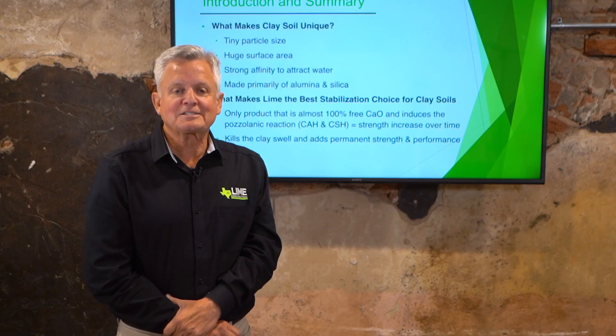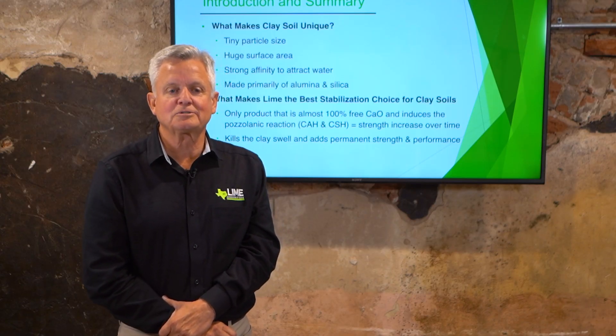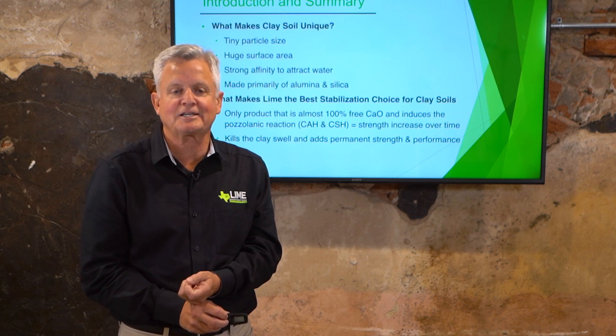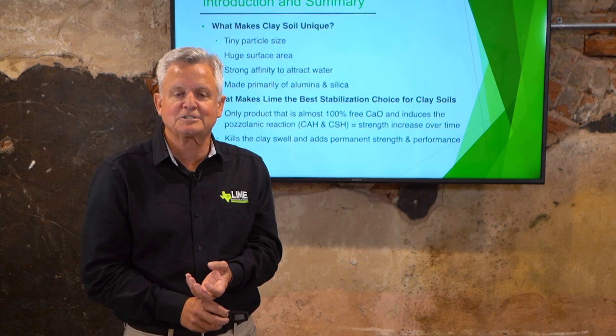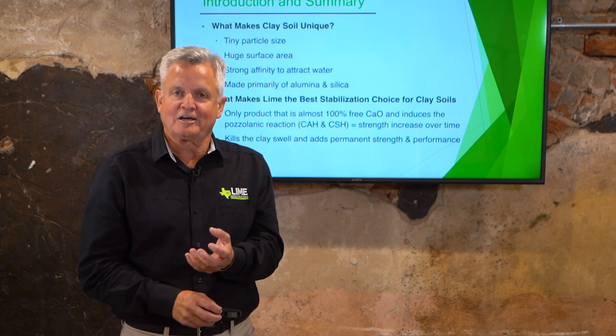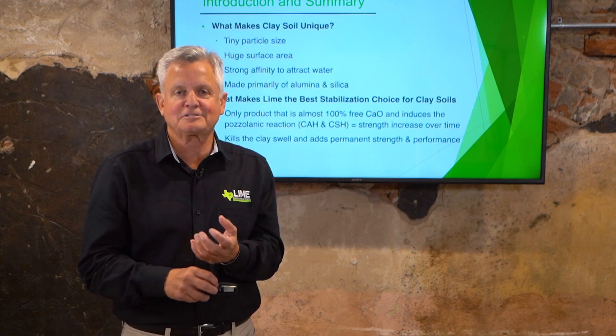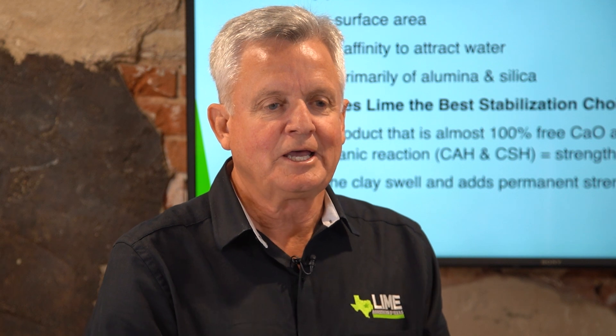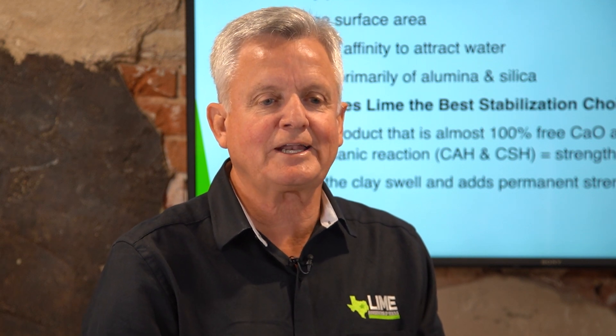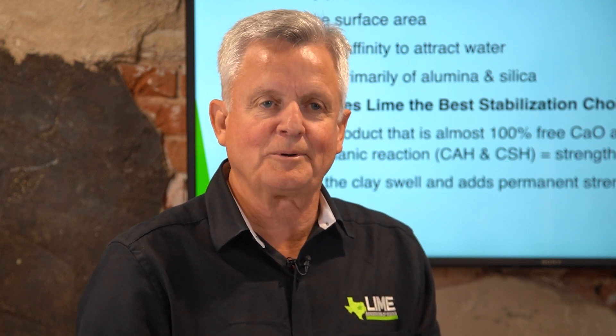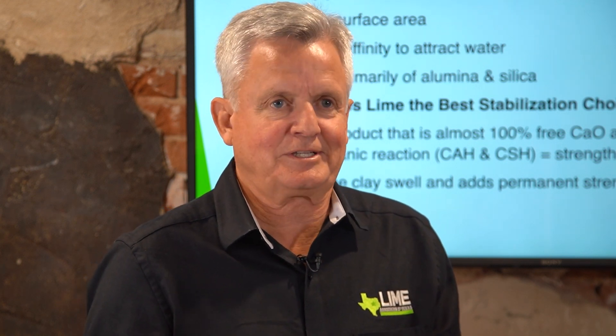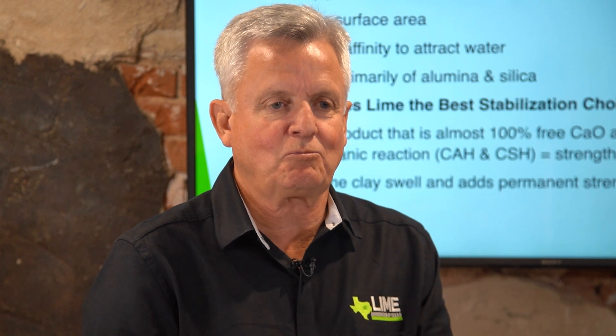What makes lime the best stabilization choice for clay soils is that it's the only product that is almost 100% free calcium oxide and induces the pozzolanic reaction — calcium aluminate hydrate and calcium silicate hydrate — which is basically forming a pozzolanic cement. It kills the clay swell and adds permanent strength and performance, making it the only product that can do all of those things at one time.